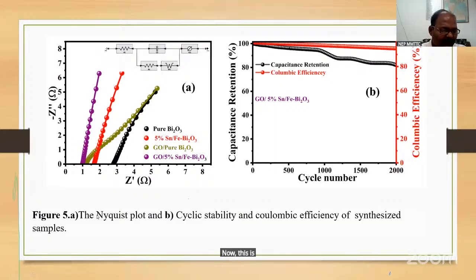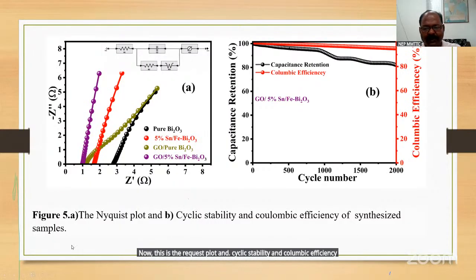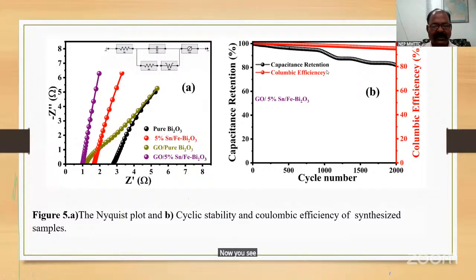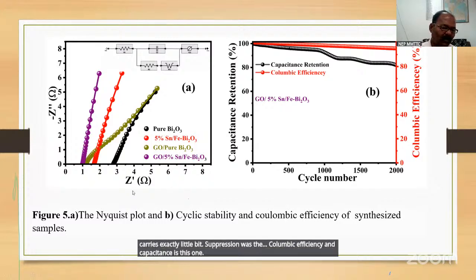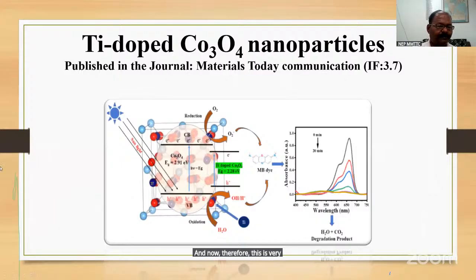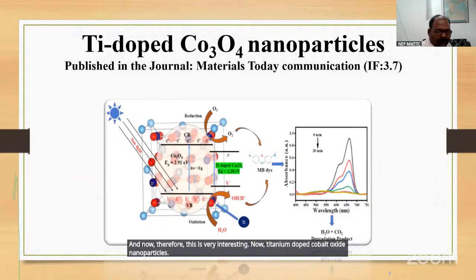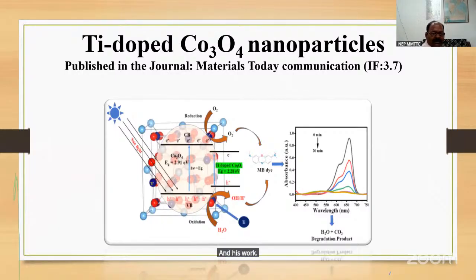Now this is the Nyquist plot, and the cyclic stability and Coulombic efficiency of the synthesized samples. Now you see the capacitance retention and Coulombic efficiency. There is a little bit of suppression here, but the Coulombic efficiency and capacitance are this one. Therefore, this is very interesting. Now, titanium doped cobalt oxide nanoparticles: this work was published in Materials Today Communications, impact factor 3.7.